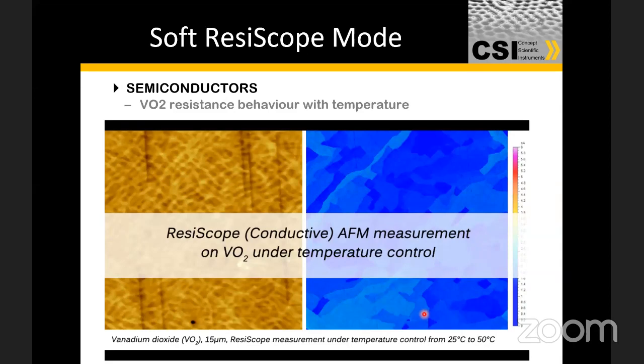Vanadium oxide, so VO2, vanadium pentoxide, these materials undergo these sharp transitions in temperature. So that's what you are showing, actually, temperature dependent transitions. So that is interesting. Right. Yeah. So this is like, classically the experiments where we could do on polymers, these phase transition experiments, where we could observe the transition from glassy to crystalline transitions. Now we're able to do that in the resistance, on these sort of materials, as you say, that are quite sensitive to temperature in their resistance performance. And it's a pretty small order, actually, it's just between 25 to 50.